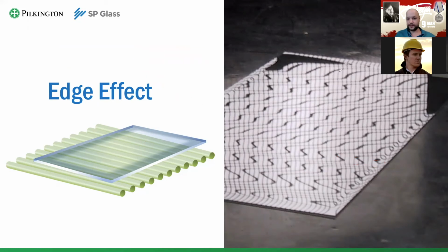Now, what else is here? What to consider for the tempering? The shorter these distortions are on the edges, the better your tempering is. When they are very short, they look very sharp, but they usually hide themselves behind the aluminum frame.